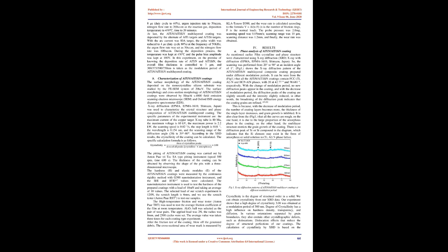Adjust the substrate bias to -800 V, -600 V, -400 V, -200 V and adjust the argon flow rate to 100 sccm. Under different bias conditions, bombard and clean the substrate for 2 minutes respectively to remove other dirt on the surface of the substrate and improve the adhesion of the film and substrate. To improve the bonding strength between the working layer and the matrix, a TiN film was prepared as the transitional layer.